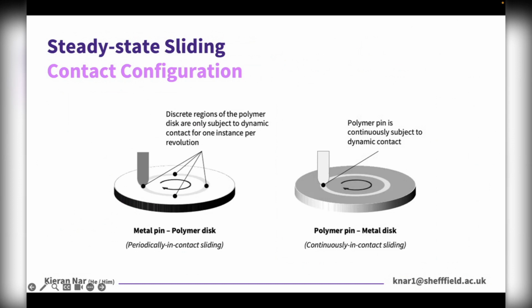As I mentioned earlier, we also carried out this testing procedure via converse contact configurations. I've just spoken about metal pin on polymer disc testing, but we also executed these tests on polymer pin on metal disc. The main difference between these contact configurations, which is mentioned in the figure, was the continuousness to which the polymer regions were subjected to dynamic contact during testing. As shown in these images, during metal pin on polymer disc sliding, discrete regions of the polymer disc were only subject to dynamic contact for 1 instance per revolution, whereas during polymer pin on metal disc sliding, the polymer pin was always subject to dynamic contact during testing.